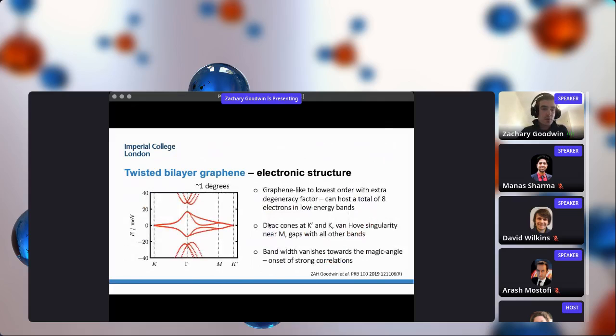Right, so if we look at a bit more of a realistic calculation for that, which is what I'm showing on the left-hand side here. So this is for an atomistic tight-binding calculation. So what we see here is we get these flat electronic states around 1 degree, and these, to lowest order, can be considered as graphene states, but with an additional degeneracy factor. So these flat bands can host a maximum of 8 electrons, and at charge neutrality, they have 4 electrons sitting here.